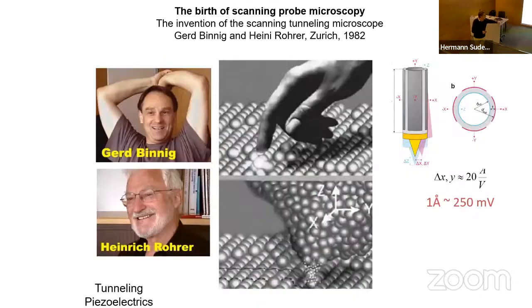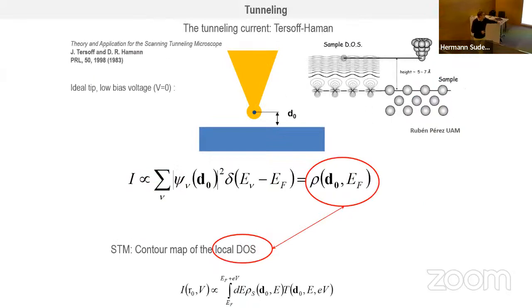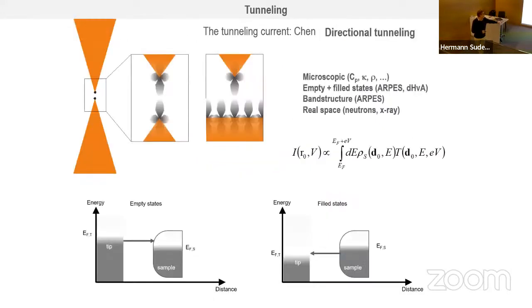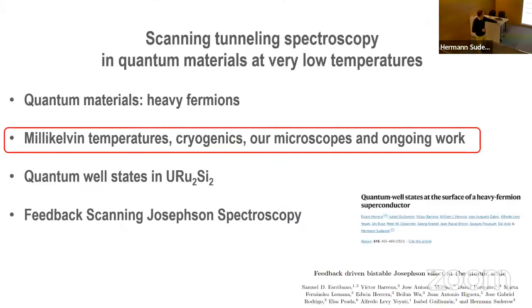So just let me briefly remind you that we are going to see STM experiments, and I don't think that I have to explain that much here, but with an STM, you essentially measure the local density of states, and you actually measure empty states and filled states. So usually macroscopic measurements like the one I have shown you just measure the Fermi surface, and with an STM you measure above and below, so you can get access to more things. Now, how do we operate our microscopes?